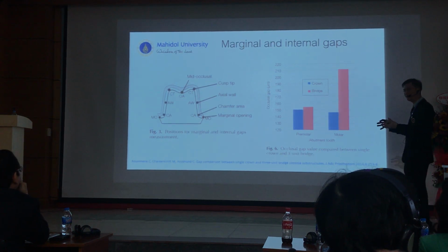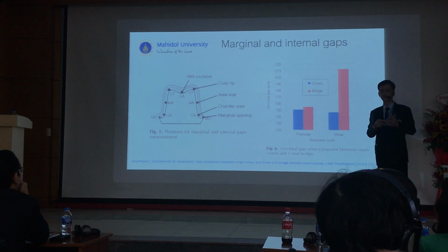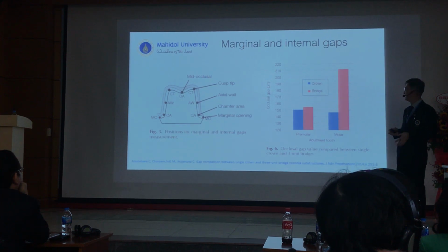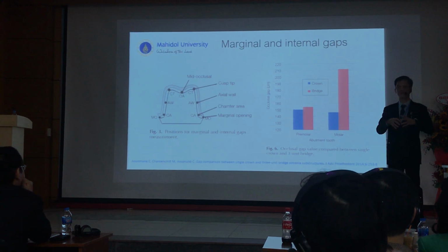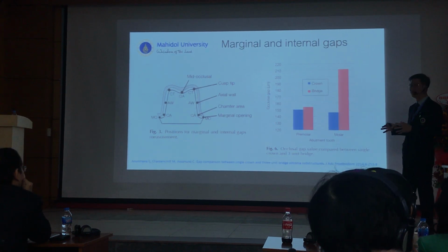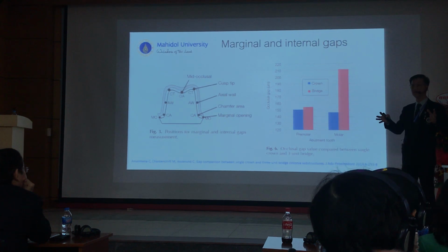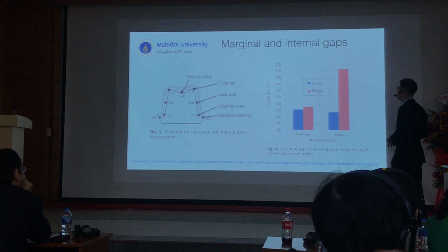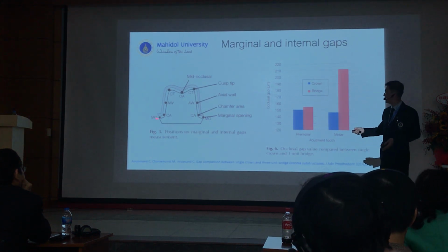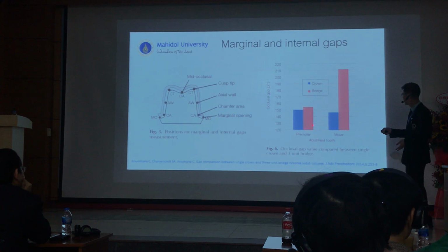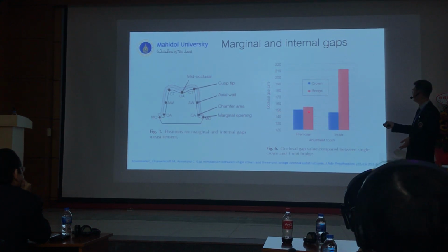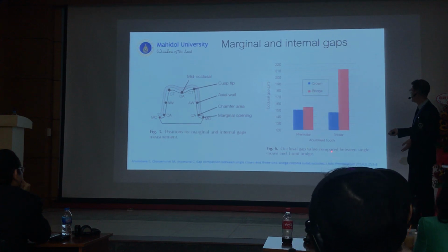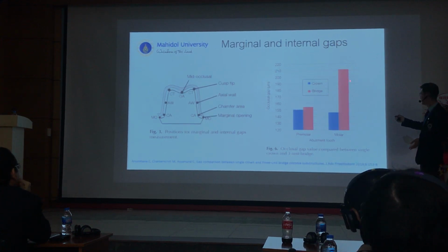You have to scan the die, the tooth structure, or the oral cavity, and then you design it with the computer. And the zirconia, you have to mill it from all sides, and then it shrinks after firing. It's calculated to make a fit at the abutment. When you do research, right now, the crown gap is okay, around 150 to 160, but when you make a bridge, maybe around 200 something.